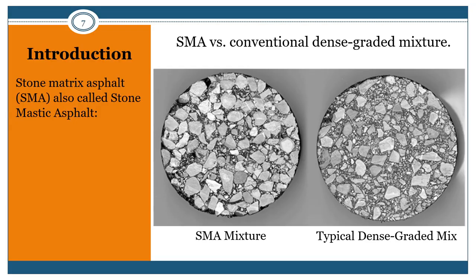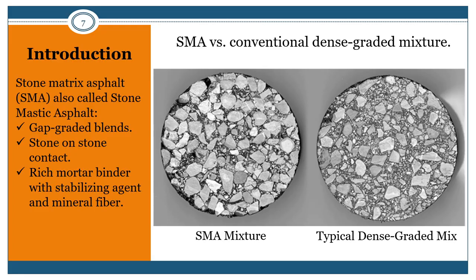For SMA mixtures, the key is to provide stone-on-stone contact with excellent internal friction so the mixture is not susceptible to lateral flow and resists plastic deformation. SMA mixtures, also called stone mastic asphalt, are basically gap-graded blends which result in stone-on-stone contact when the gradation is adequately designed. They have a rich mortar binder with a stabilizing agent and mineral fiber. They're compacted to a low air void content, and from that, they exhibit very high internal shear strength.